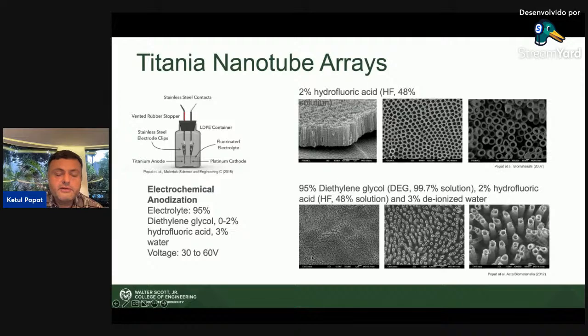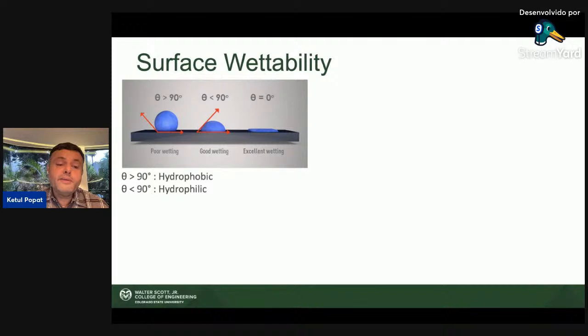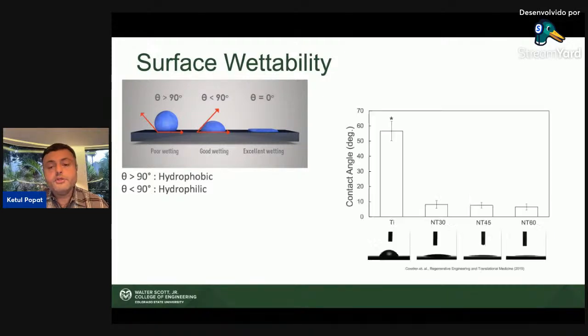So this is a very simple technique. For many years we have done that. We normally use titanium, but we can do this on many different types of alloys, and we have done it with many different types of alloys that Professor Ana Paula makes. We use some of these materials, and we can also make these kinds of nanostructures on these. The biggest advantage of these kinds of surfaces is that they're hydrophilic. Titanium is also hydrophilic, but as soon as you make nanotubes, you find that the contact angle is less than 10. So it's very hydrophilic, with very high surface energy.